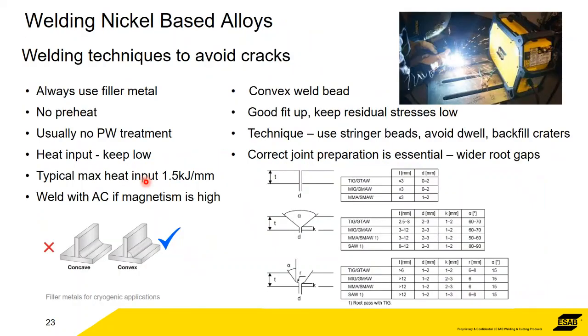But whichever is absolutely fine. In terms of the tips and tricks for welding, the techniques to use, we would say absolutely use a filler metal. If you're welding nickel-based alloys, always use a filler metal. Don't do autogenous welds without a preheat and without post-weld heat treatment. Again, something that we tend to say an awful lot is keep the heat input low. We always say that with stainless steels, with duplexes, and with nickels. Keep the heat input as low as possible, typically using a maximum of 1.5 kilojoules. We've mentioned it before, so it needs saying again. If magnetism is high, when we said that the level is around 20 Gauss, use AC welding.